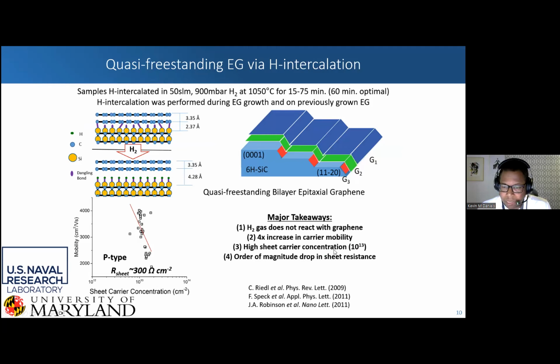Interestingly, you get this high sheet carrier concentration of 10 to the 13. And as you can see, it doesn't really matter what the mobility is, it's practically unchanging. This is really, really useful for plasmonics, as I'm going to show in a second. You also get this order of magnitude drop in sheet resistance. So it really is a very, very conductive film, with really high uniformity, which is also helpful for plasmonics.